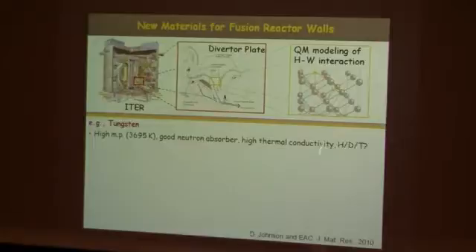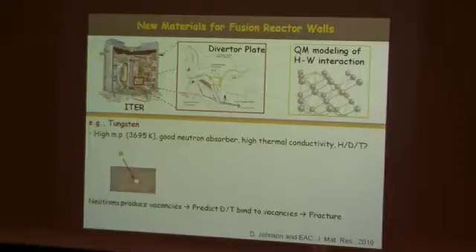But one thing that wasn't really known is how hydrogen and its isotopes, deuterium and tritium, that are formed in the fusion plasma, how they interact with tungsten. And so we undertook a study of this. We took advantage of the knowledge that this tungsten plate is going to be bombarded with neutrons. And we know that one thing neutrons do is that they produce something called a vacancy. They produce defects in the material. The vacancy just means the absence of an atom, so it knocks an atom out of place. And what we showed is that the hydrogen isotopes in a perfect crystal of tungsten absolutely don't want to go into tungsten. So that's really great because you really don't want these radioactive isotopes to get embedded inside the metal for various reasons. You don't want the reactor wall to become permanently radioactive.